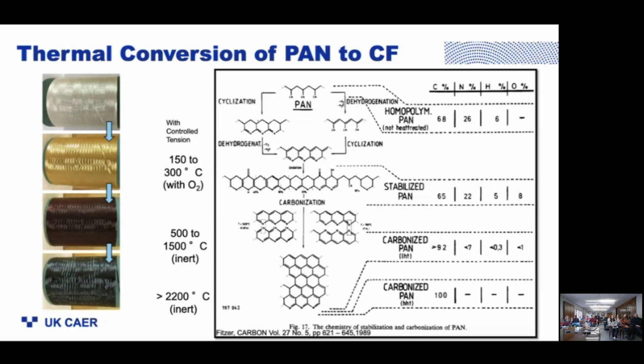As I mentioned, back to 1950, you certainly observe this color transition from white to yellow to brown to black as we go through chemical transitions associated with the cyclization of the nitrile group on the polyacrylonitrile, forming these intermediate cyclic structures, which have some measure of oxygen functionalities on them. That's what we call the stabilized polyacrylonitrile, which is ready to be subjected to the high temperatures of carbonization, done usually between 500 and 1500 C for most of our standard and intermediate modulus grade carbon fibers, and some heat treated above 2200 C to form higher modulus carbon fibers.